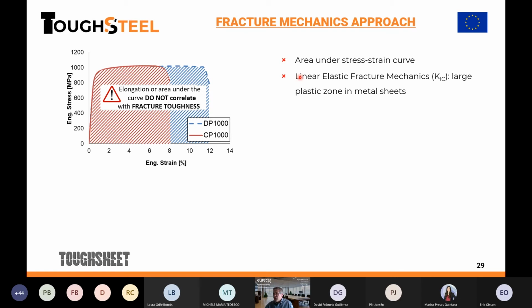We cannot use linear elastic fracture mechanics because the steels are ductile, so the plastic zone is high. We cannot use the easy plane strain fracture mechanics. We have to come to elastoplastic fracture mechanics. And here we have old, well-established methods like the J integral, the JR curves, the CTOD.